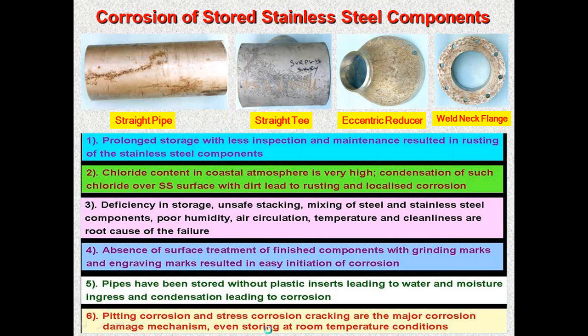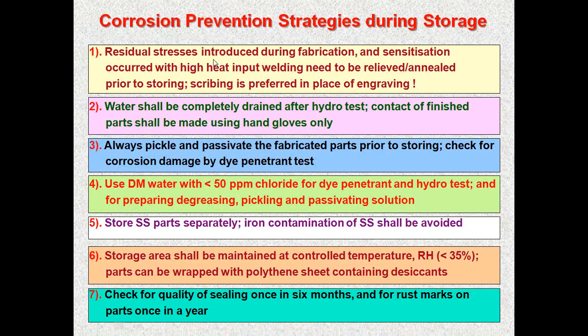How do you then avoid this? Please take care that residual stresses introduced during fabrication, and sensitization that occurred with high heat input welding, are relieved and annealed prior to storing. This is very important. If you want to identify parts, scribing is preferred in place of engraving. Water shall be completely drained after hydro test. Contact with finished parts shall be made using hand gloves only, if it is a very finely finished part or in pharmaceutical, food, beverage and maybe nuclear applications.